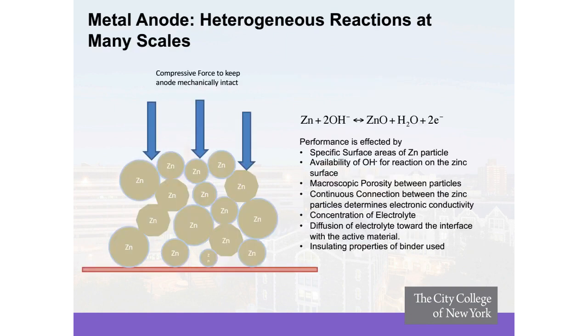If one were to focus on the particulate nature of the zinc anode, one will understand that the zinc particles, as they undergo corrosion, actually only their surfaces corrode. And very much as a core shell model, the oxide surface increases in size and eventually dissolves in the electrolyte. The metallic particle begins to decrease in size, and the biggest problem that one runs into in these kinds of situations is that the particle-particle contacts begin to diminish or are completely eliminated, and so the actual conductive pathways for electrons to allow for the corrosion process to occur are eliminated, and there is no conductivity pathway to the actual interface between the zinc and the electrolyte.